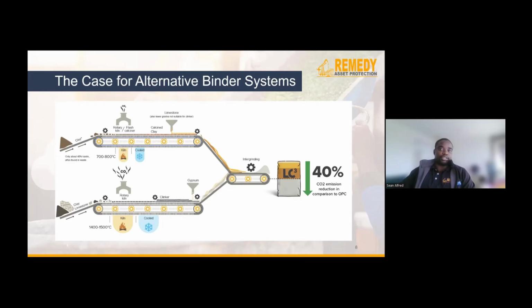And this is because in the production of the calcined clays, they're more malleable and heated at about half the temperature as you would in normal clinker production of ordinary Portland cement.